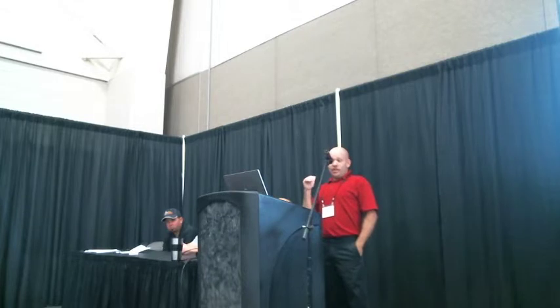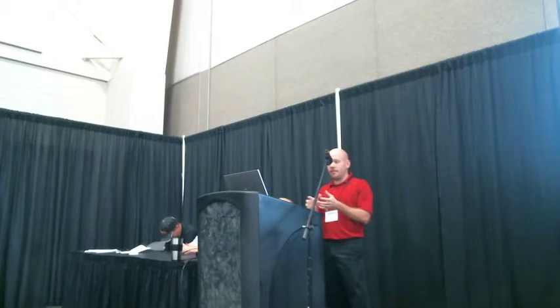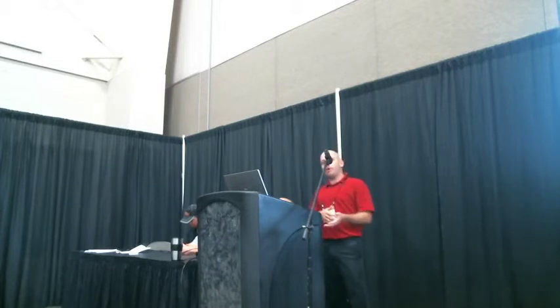No one has really done it with 100% mill tailings, so we took some research from Spencer Guthrie, and it's shown that you want an unconfined compressive strength of about 300 to 500 psi at 7 days, which I'll talk about being the testing requirement. And it was really a shot. So it's just with cement treated base, the more cement you put in it, the stronger it'll be. So the real question is, how much cement do I put in? And that's the report we used from Spencer.